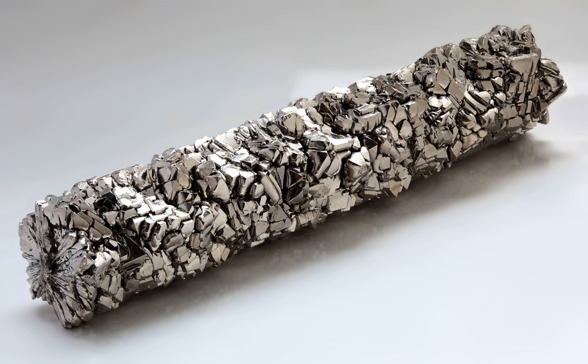Fresh metal may be exposed when the oxidized surface is struck or scratched with a hard object, or when mechanical strain causes a crack. This poses a limitation to its use in liquid oxygen systems, such as those in the aerospace industry. Because titanium tubing impurities can cause fires when exposed to oxygen, titanium is prohibited in gaseous oxygen respiration systems. Steel tubing is used for high-pressure systems (3000 psi), and aluminium tubing for low-pressure systems.